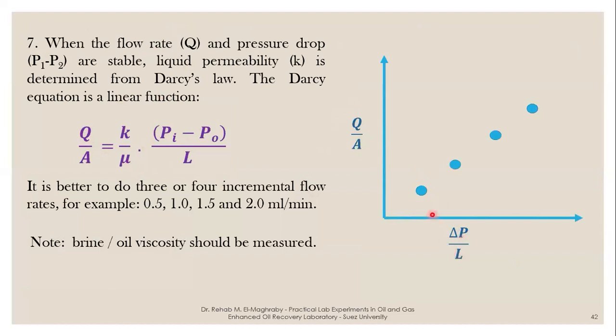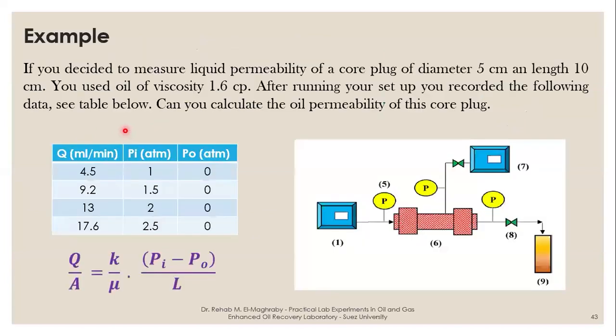The length is constant. You draw Q over A on the y-axis. On the x-axis you have delta P over L. So you will have a straight line. The slope of this straight line is K over mu, where mu is viscosity. K is actually the permeability, the absolute liquid permeability that you have.